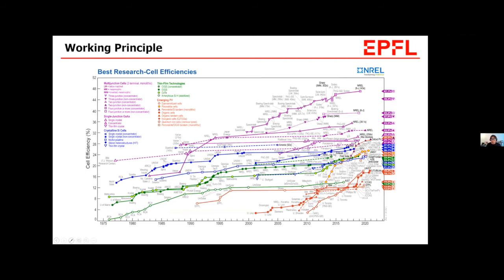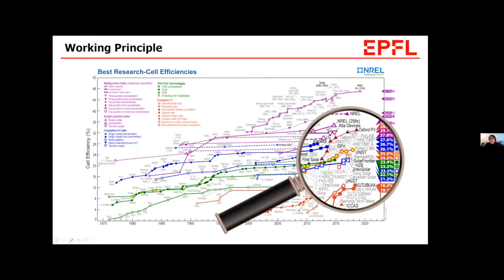So where are we now? This is the NREL chart showing the power conversion efficiency of certified solar cells. The efficiency of perovskite solar cells in this chart started from less than 15% in 2013, and now it is 25.5%, which is very close to the efficiencies of silicon solar cells. Now I'd like to introduce how perovskite solar cells have evolved in chronological order, from the first perovskite solar cell, and some works that I think of as breakthroughs.